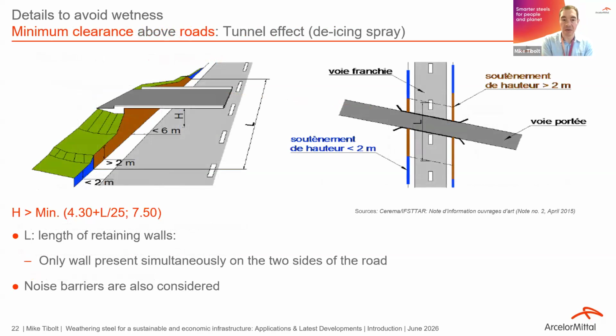Also, the height above the road should be respected. This is a recommendation coming from France to avoid what we call the tunnel effect. Depending on the distance from the walls, from the road, and also the height of these walls, you should have a minimum clearance between the road and the bridge. It can go up to a minimum of 7.5 meters, so quite high. This is exactly to avoid the de-icing spray effect when the cars run below the bridge.